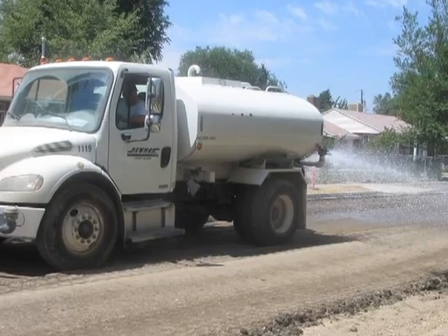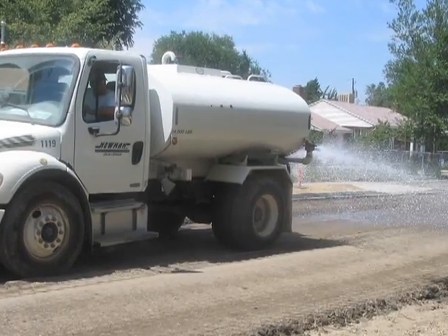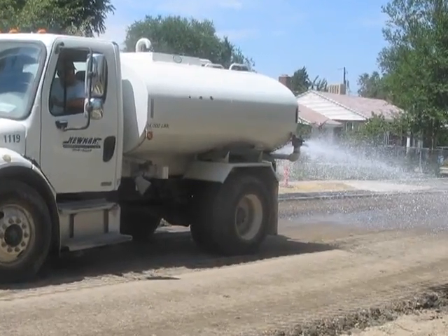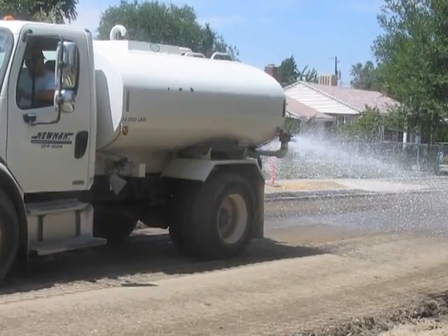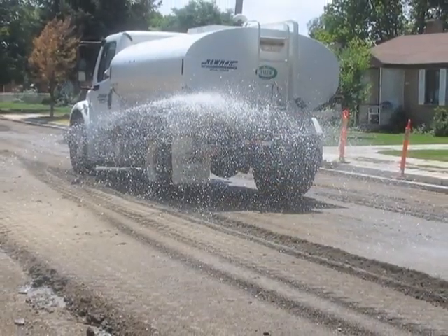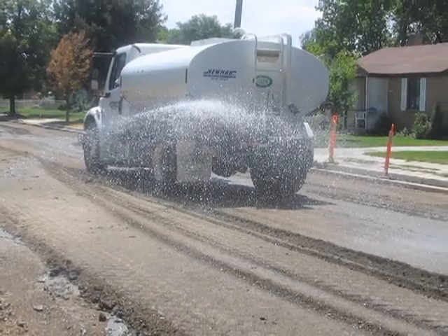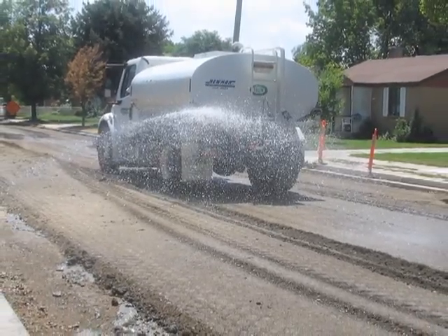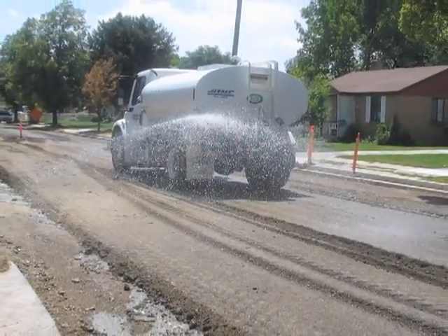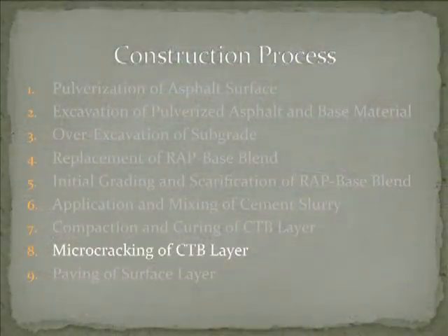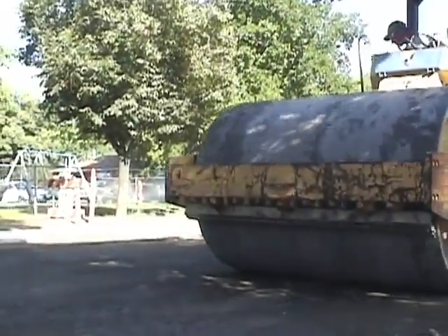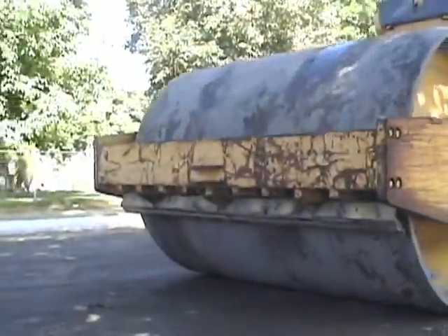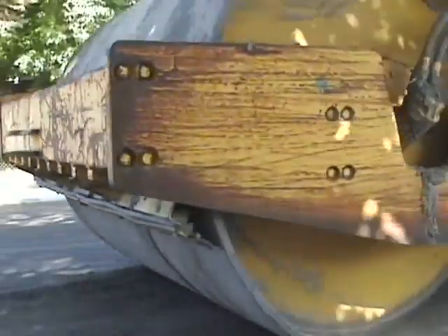Proper care needs to be taken when curing CTB. Cement requires proper moist curing to ensure that enough water is provided for cement hydration. The moist curing process was ensured by spraying the CTB with water using a water truck. 8. Microcracking. Microcracking was performed 2 days after the final compaction of the CTB. An 8-ton vibratory roller was used to microcrack the new CTB.